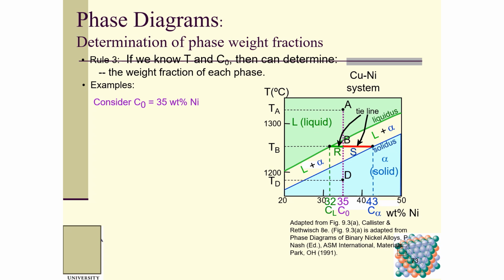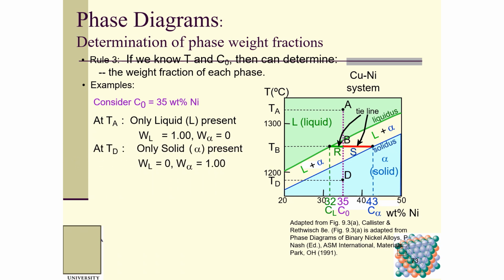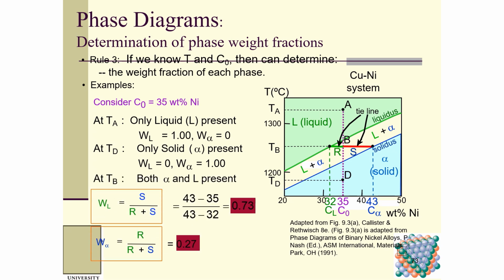So for example, still using this example, we draw the horizontal line here, CL, C alpha, right? At TA, we only have liquid, 100 percent, alpha is 0 percent. At D, solid is 100 percent, liquid 0. At point B, we draw a horizontal line here, and both alpha and L are present, and you can see WL, the liquid weight fraction. For these two equations, the denominators are the same, but pay attention to the numerator, okay? For liquid, we use one arm, and for solid, we use the other arm. You need to be very, very careful here, otherwise your answers will be wrong.